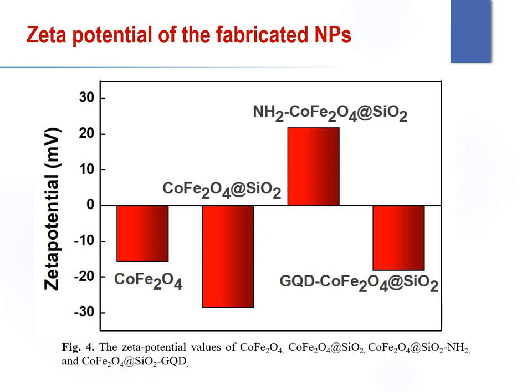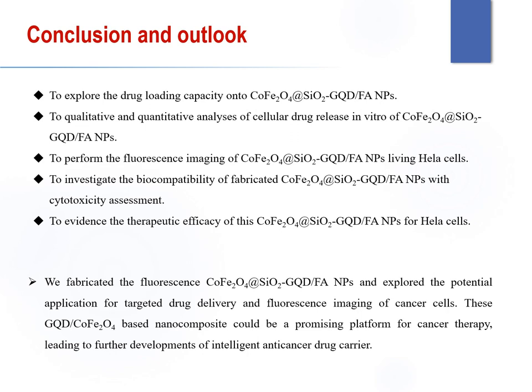The measured cobalt nanoparticles modified with silica show a negative zeta potential, as expected from the surface silanol groups, confirming that the cobalt nanoparticles were successfully covered by the silica shell. The potential of the amine-functionalized cobalt nanoparticles shifts toward the positive side, confirming successful modification with the amino groups of APTES. Finally, the negative zeta potential of the cobalt silica connected with GQD indicates successful covalent bonding between the GQDs and the silica nanoparticles.